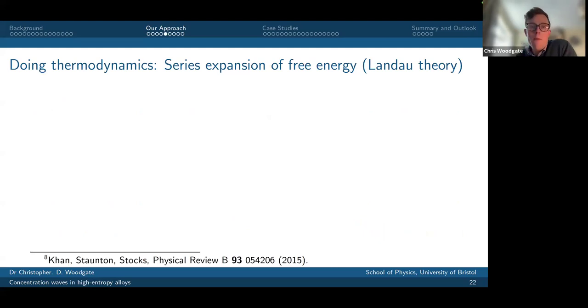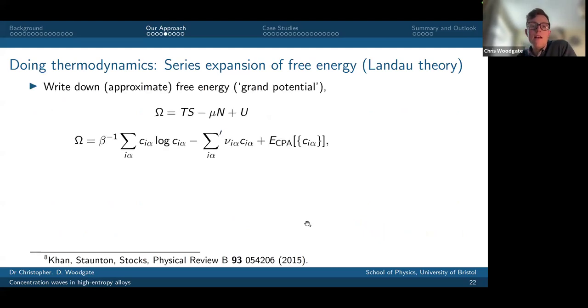Okay, so this is where we come at a Landau-type theory for the free energy of the system. To assess ordering tendencies, we write down an approximate free energy. So omega is Ts minus mu n plus U. In the theory I'm using here, Ts is the sum over lattice sites of the entropy of mixing. Mu n is the mu_alpha c_alpha term; these actually act as Lagrange multipliers in the theory, helping to enforce the overall concentration of each chemical species. And then U is the internal energy of the alloy as described via the CPA.